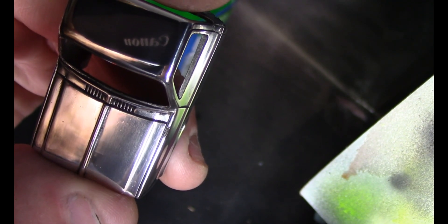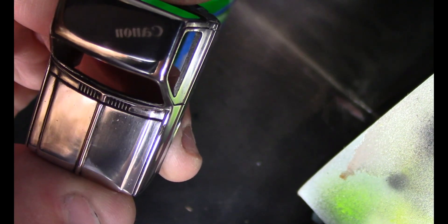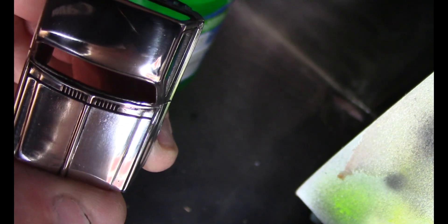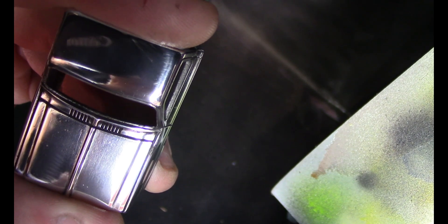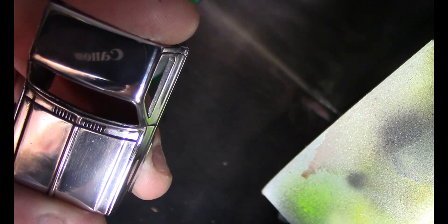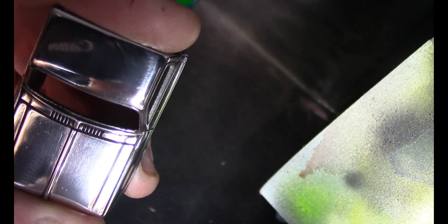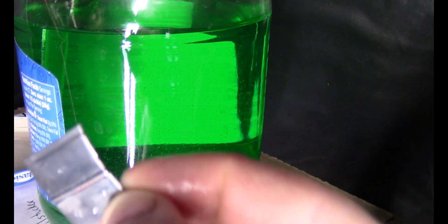Now here's after I finished polishing the truck and you can notice in the reflection that one half has a more crystal image than the other half. The side with the more crystal image I didn't apply as much pressure when polishing it with the buffing wheel, and as a result it didn't heat up as much and the buffing wheel didn't remove as much material, so it gave a nicer finish.